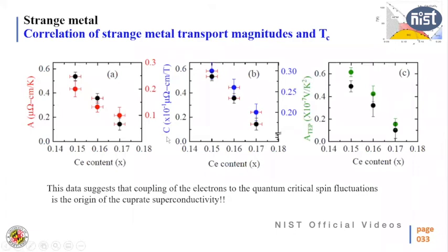Now, there are some theoretical explanations that this linear in T resistivity could be due to spin fluctuations, which is related to some sort of quantum critical behavior. So what it tells is that superconductivity is probably linked to spin fluctuation. That was one of the findings in these materials.